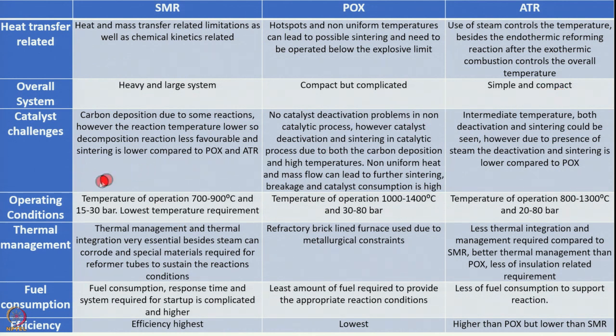compact for autothermal reforming. There are several catalyst related challenges like carbon deposition in case of steam methane reforming, but these are comparatively much less than the other two processes because the reactions which produce carbon either dominate at the very low temperature regime or are not much favorable in the temperature in which the reformer operates. In non-catalytic partial oxidation, there is no catalyst deactivation problem, but in catalytic partial oxidation, both the problems related to deactivation and sintering are there, and non-uniform heating and mass flow rate can lead to even catalyst sintering, breakage and consumption. In autothermal reforming, the challenges are sort of intermediate. Deactivation and sintering are there, but due to the presence of steam, deactivation can be reduced and sintering is lower than in partial oxidation.